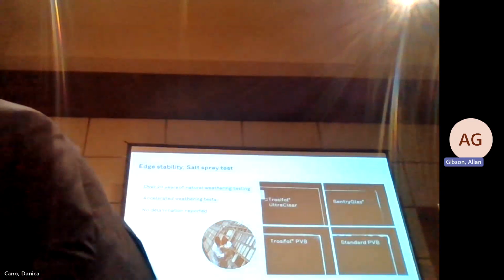ASTM B117 is a 3,000-hour test at temperature with a relative humidity of 100% using a saline solution. The top two samples show no effect, but the bottom two samples show signs of moisture ingress due to the hygroscopic properties of PVB. It becomes milky and cloudy around the perimeter of the panel, and over time it will affect the transparency and the visual effect of the laminated glass. Worst case scenario, it will delaminate over time.